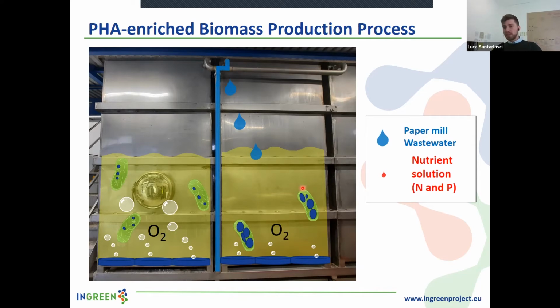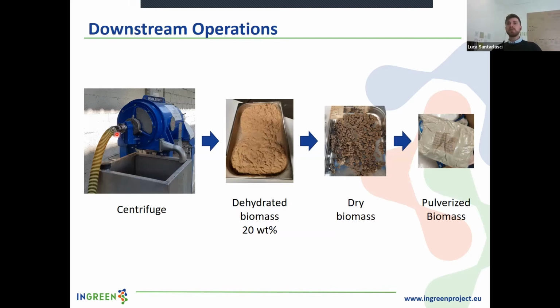When the PHA accumulation is completed, the biomass is dehydrated using a centrifuge in order to get a sludge with a solid content of about 20%. Then the residual 80% of water is removed by keeping the wet biomass at 60 degrees Celsius for a few days until the complete drying of the sludge. And finally, the dry sludge is ground using an electric mill in order to get a fine powder which can be easily processed for further steps.